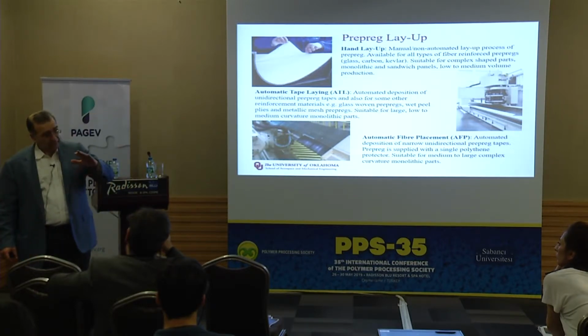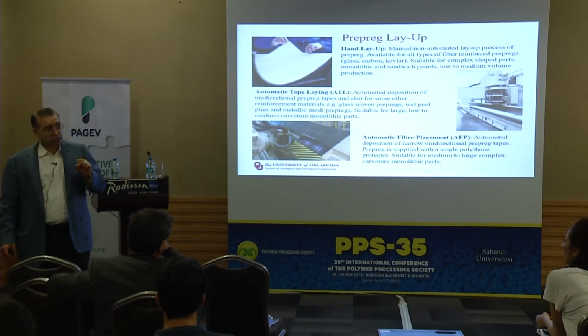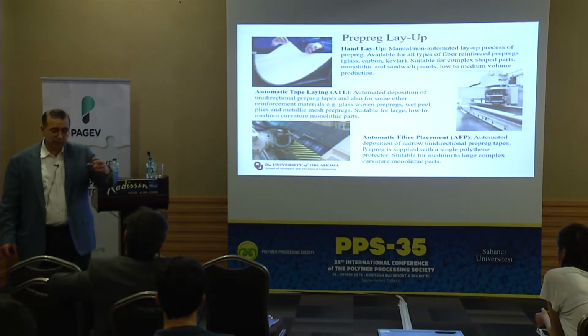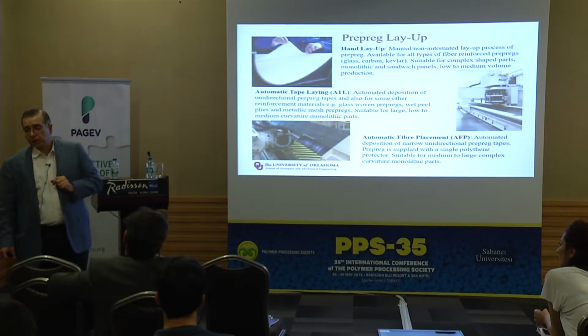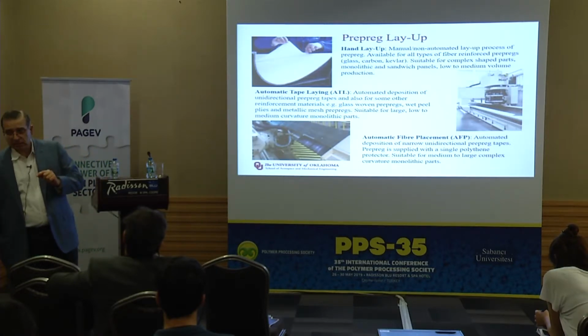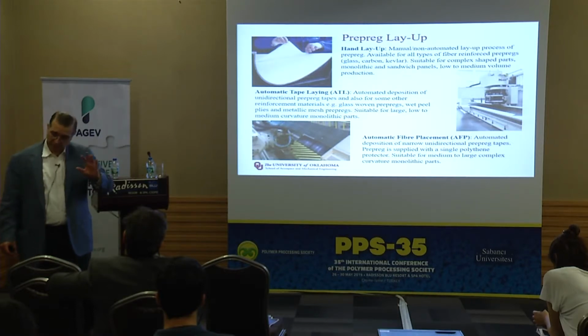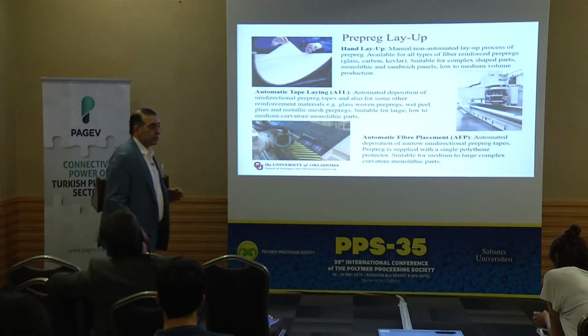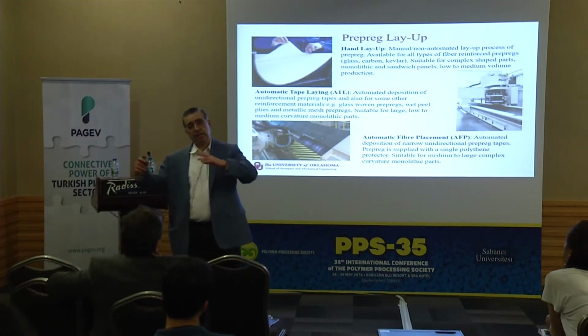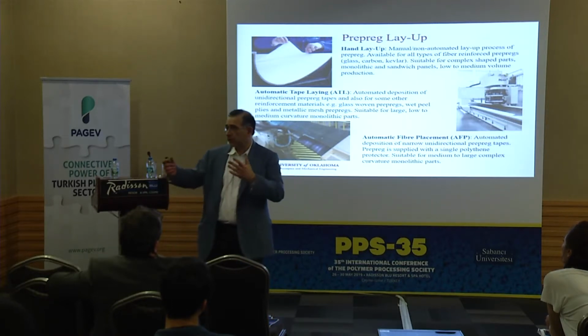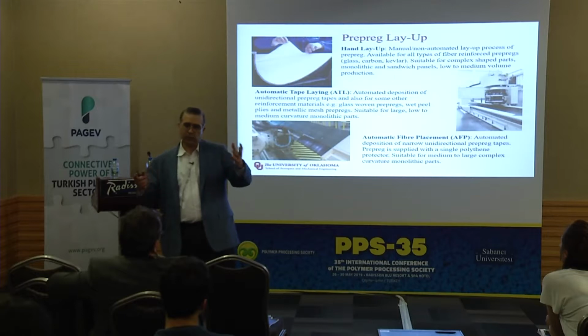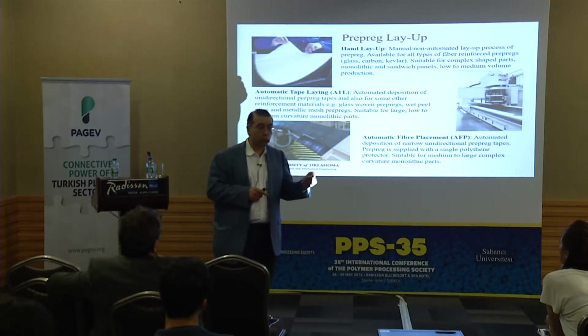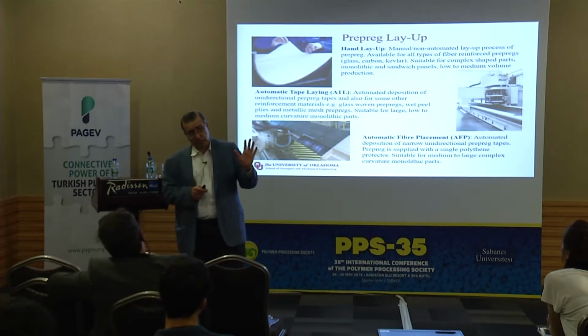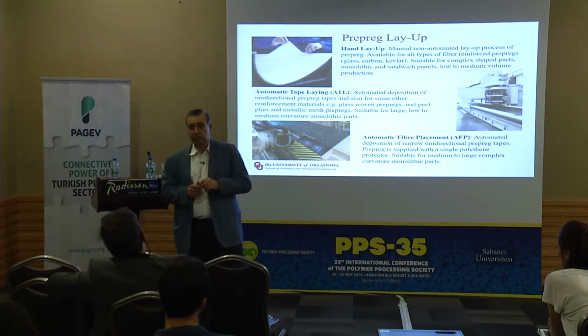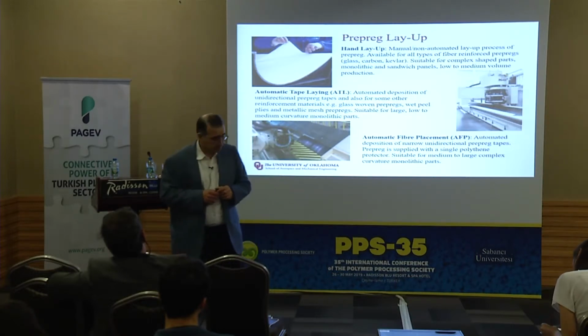When you make a laminate with the prepreg that contains moisture, the water is expelled during cure, okay? But it may not leave the laminate, so it may essentially leave micro voids. So your void content will be much higher in the final laminate. Now, we have not really talked about voids, but there's another group of people, maybe 24 in the world, who all they do is void, and we have done a lot of studies in formation of voids, because voids in thermosetting resins are the primary defect that creates lower performance.